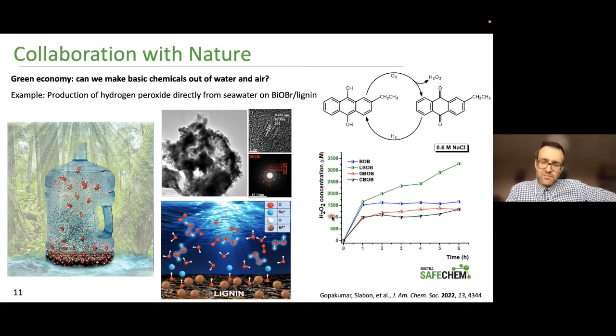You see the produced concentration of hydrogen peroxide from seawater. It's in micromoles. The scale goes to 3000 because the standard is usually in micromoles. And here's the time. So here's the generated amount of product. And you see, if you take a look at BOB, that's the pure inorganic catalyst with bismuth oxygen bromide, it kind of stops at a certain point, but if you grow it on lignin directly, you get the best performance actually. So it pays off to make green chemistry. That's what I want to say here, because you get the best performance and also work with nature's biodegradation mechanisms.